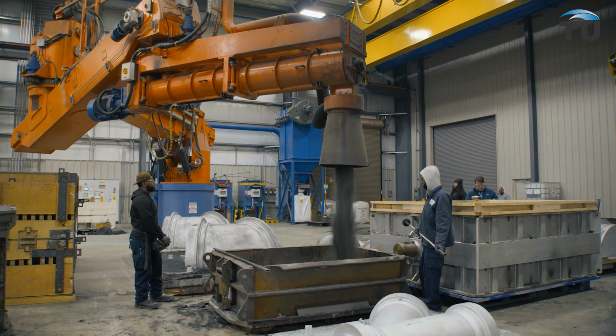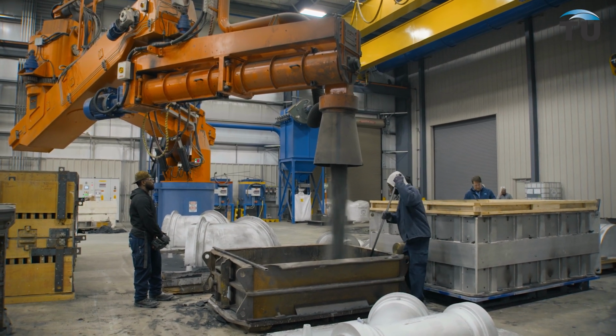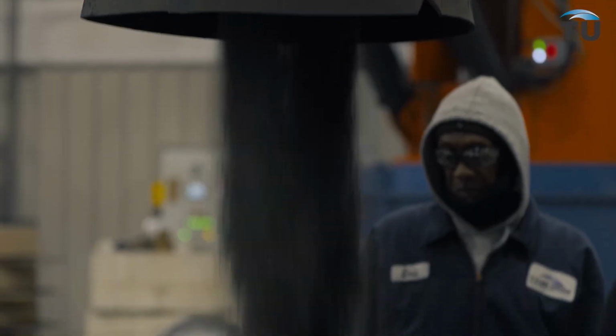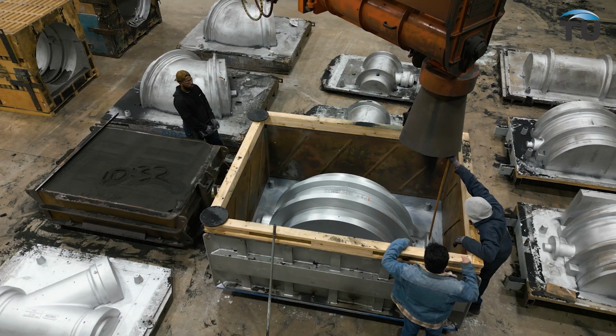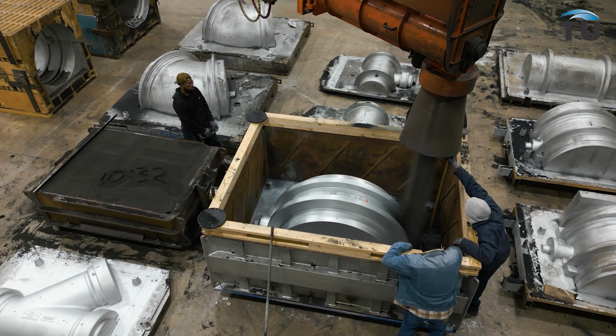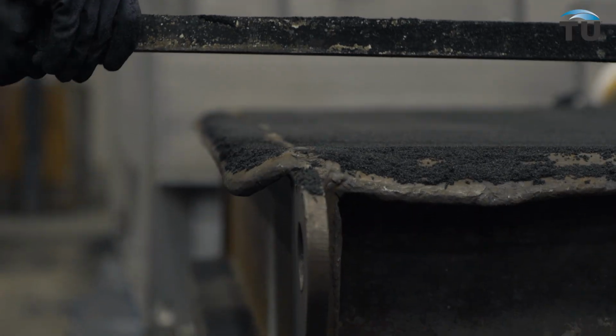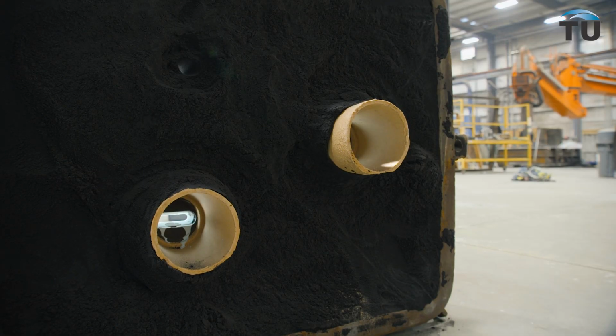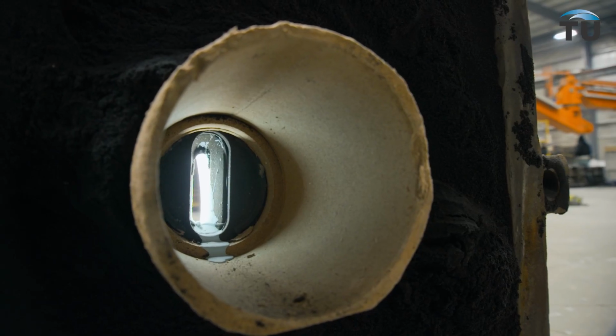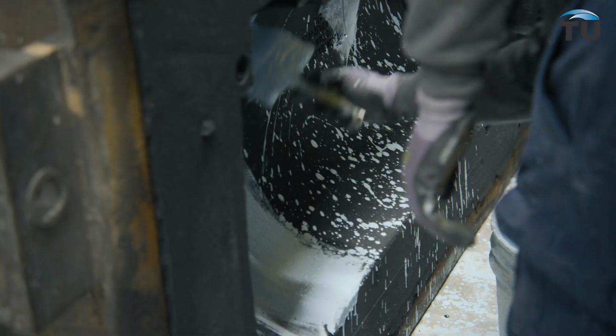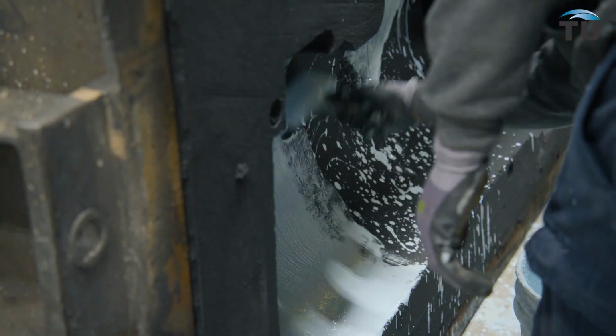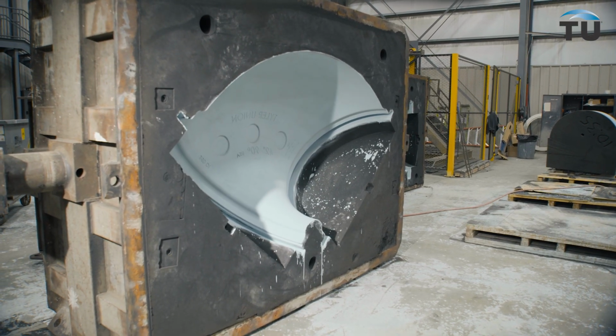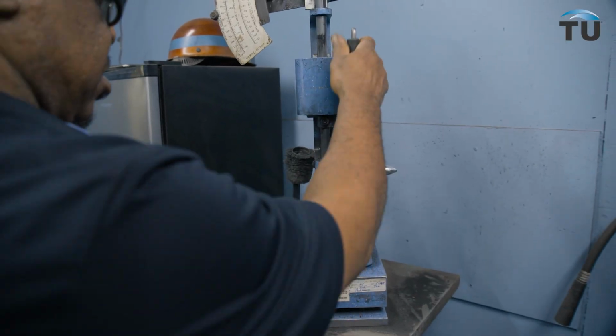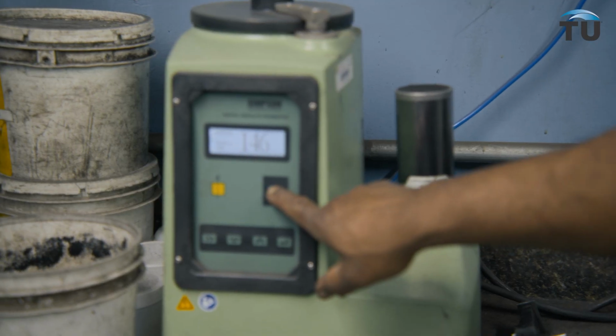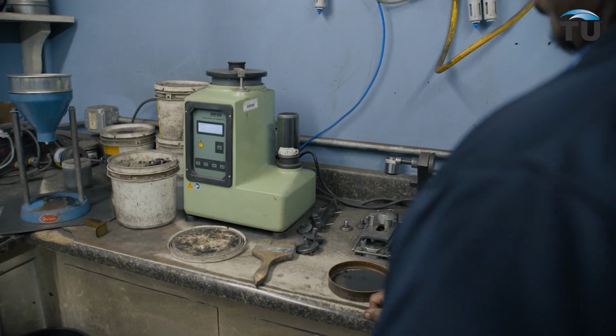Before pouring, a large continuous sand mixer blends furan resin and a catalyst with sand. The mixer can output 30 to 60 tons of this sand per hour into mold flasks placed underneath. When flasks are filled, the sand is manually smoothed to ensure consistency, and the gating channels are created through which the molten ductile iron will travel. The core is then set in the mold, and a core wash is applied to ensure a good surface finish on the castings. The sand used is routinely tested for strength, pH, moisture, loss on ignition, and grain size distribution.